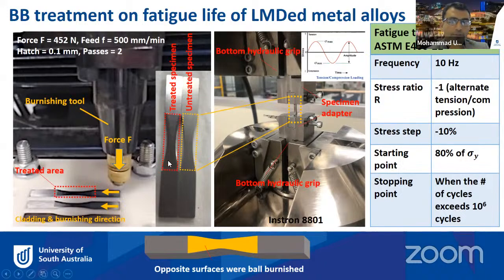So we prepared the fatigue specimen, a dog bone specimen like this, and we ball burnished it. We ball burnished both surfaces of the dog bone specimen, and then we put this specimen onto the Instron universal metal testing machine, and we applied cyclic loading at 10 hertz. And then we looked into the number of cycles until the material fails.